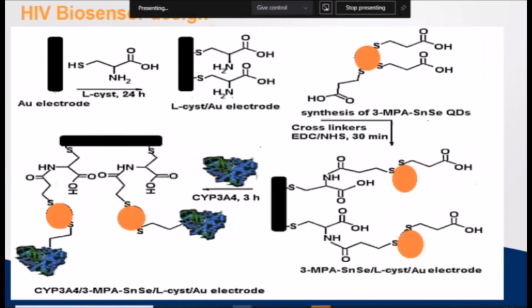Now this is a simple design of the biosensor system. In this case, we developed an ARV biosensor system. We were using a gold electrode as our working electrode, and then we modified it with L-cysteine or L-cysteamine. There are reasons for including L-cysteamine or L-cysteine onto the gold electrode surface. The reason is that